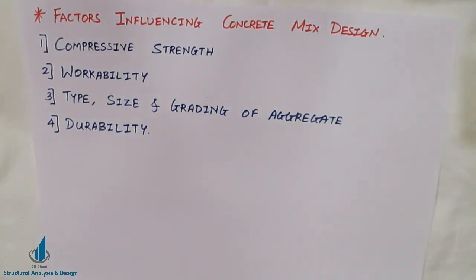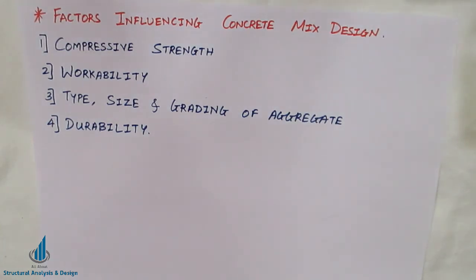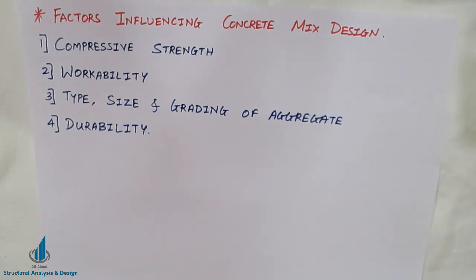The next influencing factor is the type, size, and grading of aggregates. Good concrete can be made using irregular gravels and crushed rock, which are mostly angular in shape. The maximum nominal size of aggregate depends on the width of the section and spacing of reinforcement. Grading is a major factor influencing workability — it should ensure that voids between larger aggregates are filled with smaller fractions and mortar to achieve maximum density and strength.